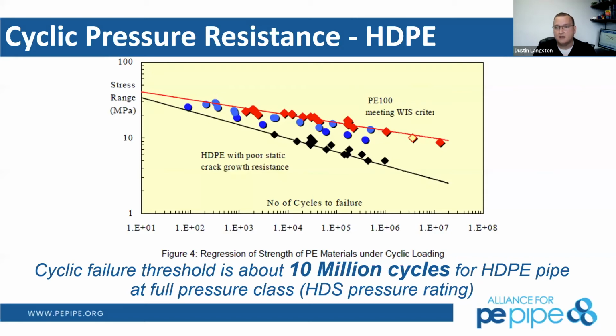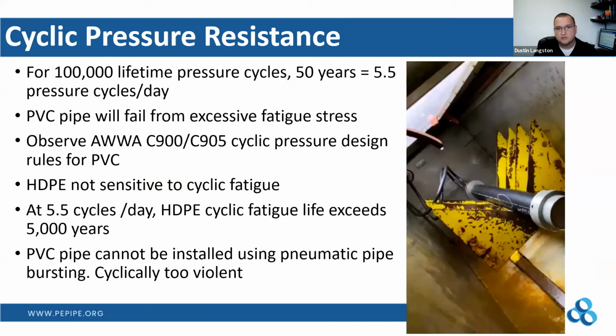And so we actually had a University of Texas Arlington study on polyethylene pipe, DR17 rated 125 PSI, taken to 2 times pressure class, so 250 PSI, over 10 million cycles. And then my favorite part that wasn't in that report: Harvey Svetlik, who Peter mentioned before, provided the pipe for this testing. He took some of that pipe sample off test and then tested it for new pipe criteria, tensile strength, elongation, all those things, and it still tested as brand new pipe. So again, cyclic fatigue for polyethylene pipe is not an issue.